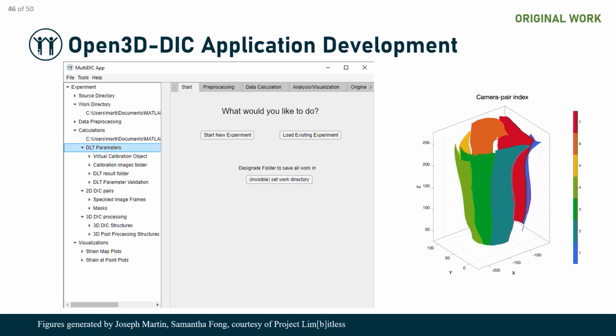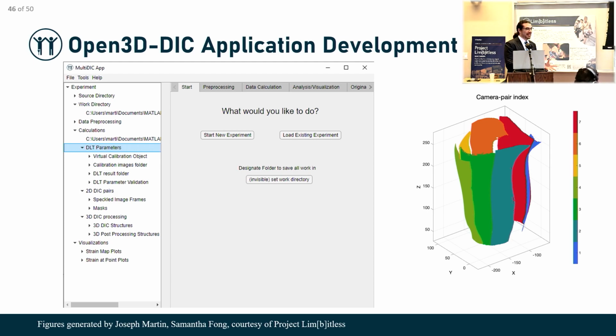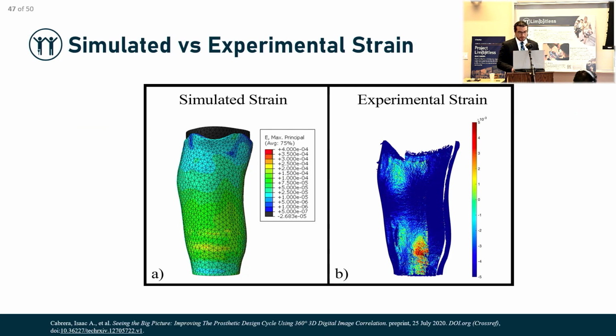But of course, things are not as easy as you think. Even though we built that whole system, we also had to build the software to analyze the strain data. So we were building off of an open source package from MIT called Multi-DIC, and we created an automated way of doing that strain processing using the algorithms the MIT team developed. And what you can see here is that we were able to reconstruct the socket in 360 degrees, and we're able to get the actual true strain on the surface.